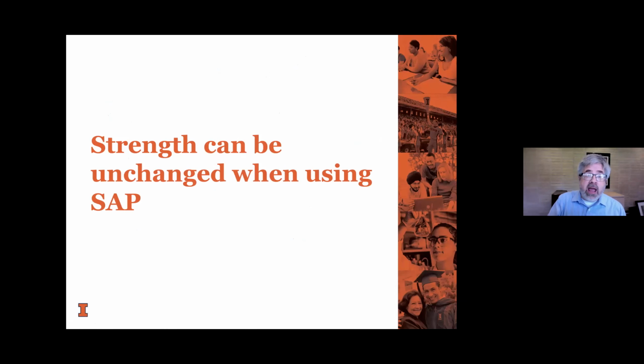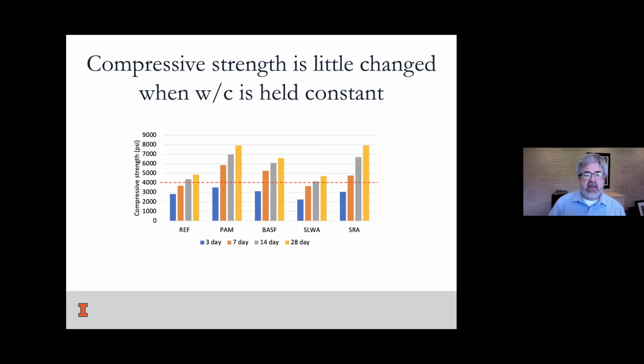If we are able to add it, such as we saw with method A, our water cement ratio is not going to be changed. We would hope that perhaps the strengths are going to be the same. Good news, in fact, all the testing seems to say that's true. We basically have sets of different kinds of materials that we've tested, and the strengths are either the same or even maybe a little bit improved because of this more effective internal curing and the distribution.